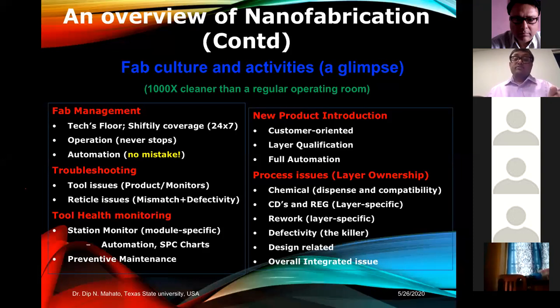You have to scrub that layer. But then when you scrub it, you cannot impact the layer underneath. And that is what brings it to a more complicated situation that you have to deal with. So then you have to define the layer specific rework process. When you want to rework it, you scrub it, but then you have to define what chemical you are going to use and how long and what is the rate and how you are going to do it so it doesn't impact the underneath. Okay? And then you can redo it, and then you can adjust, you can tweak your process, so you can get it to 30 nanometer. So that is the rework process you have to define.